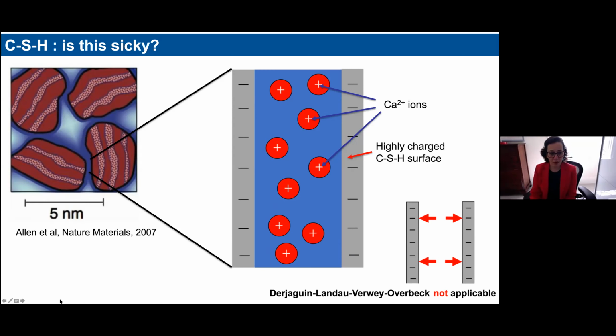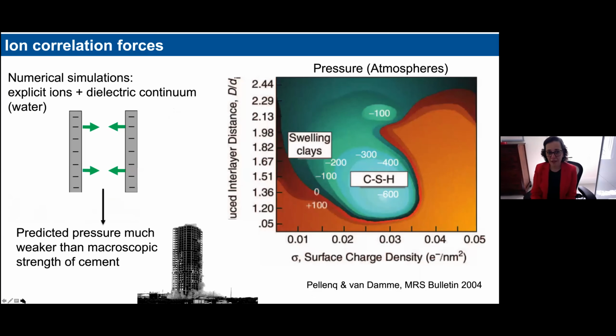And so the point is that you can put these ingredients in Monte Carlo simulation, as has been done, to see that for the surface charge and the type of ions that you have in CSH, these are data from a study done on clays, you can see that there are regions of this phase diagram, with the interlayer distance and the surface charge density, that correspond indeed to calcium silicate hydrate, where you end up having the attractive interaction.